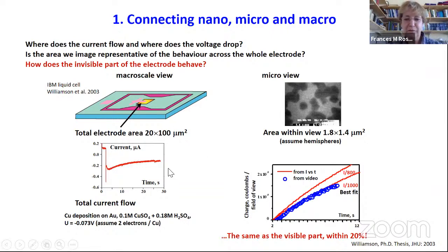So here's an example from those movies I showed earlier. We do this for all of our experiments. Here's the current versus time transient for this movie. We can integrate the charge that flowed. We can work out how much copper it represented. We can see how much copper was on the field of view if we assume that these are hemispheres. And then we can match those things up. And amazingly enough, the electrode as a whole behaves like the tiny piece you imaged pretty closely. You get a very good match between these two things. So this is one of those basic calibration things you should think about when doing these experiments.